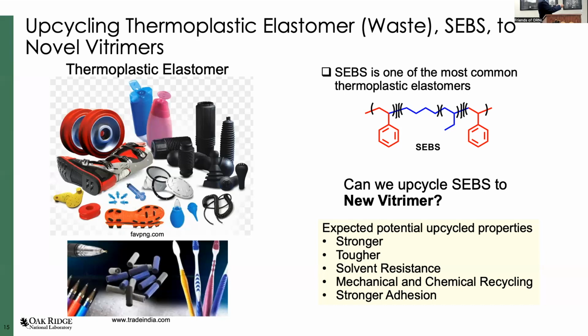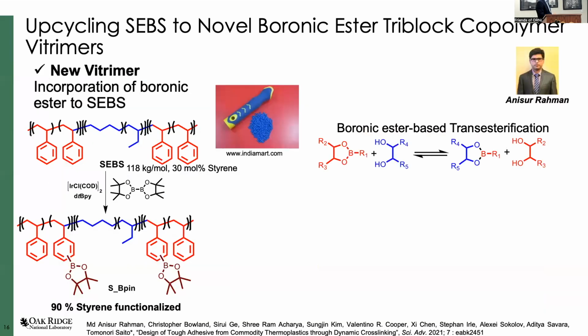So can we make this a vitrimer from this? One of the typical materials is SEBS, styrene-ethylene-butylene-styrene, a tri-block polymer. Can we modify it, make it stronger, tougher, solvent resistant, and still recyclable? Also maybe improve adhesion. So that's what we started looking at. This is a little more chemistry: the existing plastic is a thermoplastic elastomer, the typical material like this. We did one-step functionalization, the boron ester functionalization.